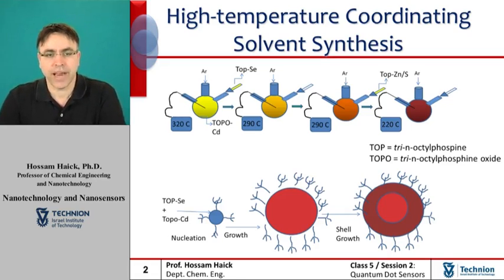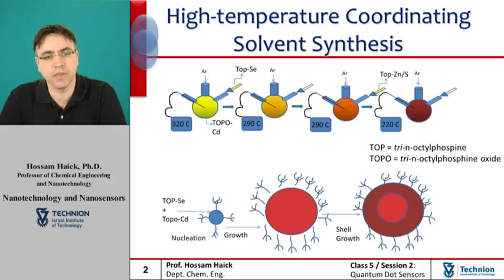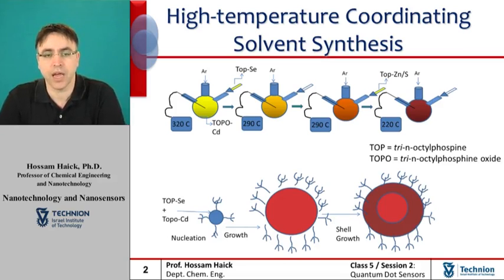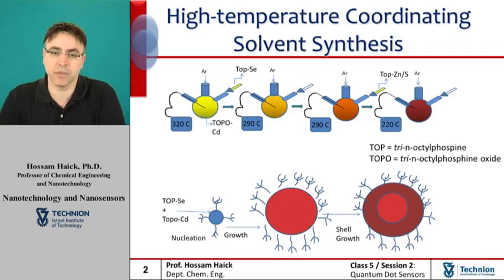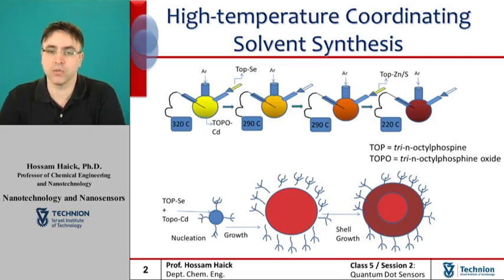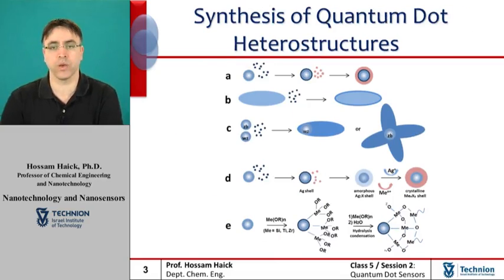Although the reactions carried out to produce quantum dots must be performed under an inert atmosphere due to the reactivity of the precursor species with oxygen, the quantum dots themselves are stable in air. Therefore, post-synthesis manipulation can be carried out in air, making the quantum dots relatively easy to work with.